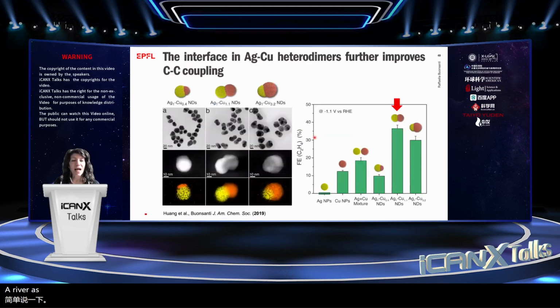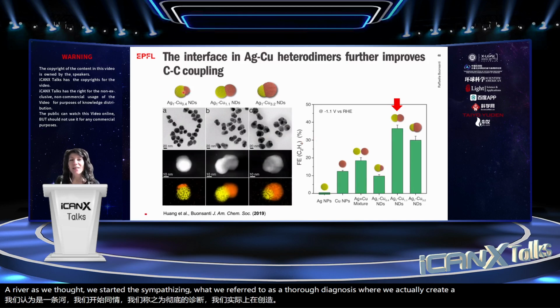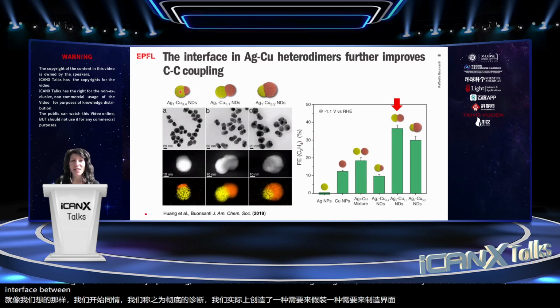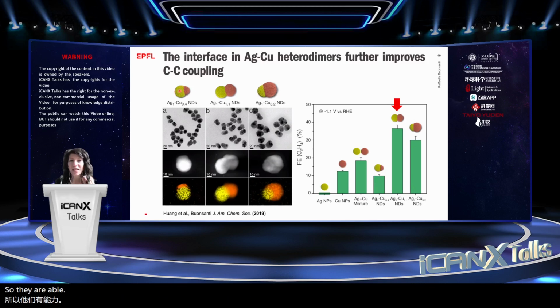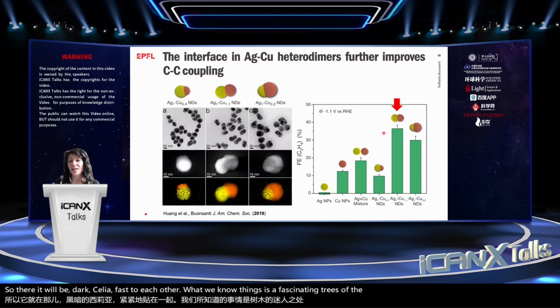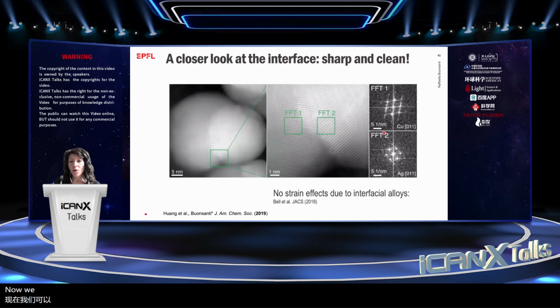However, as we started synthesizing what we refer to as heterodimers, where we actually create an intimate interface between the silver and the copper, so they are heteroepitaxially attached to each other, what we notice is a further increase of the Faradaic efficiency towards ethylene. Now, we performed some analysis on the as-synthesized particles, which revealed that we have a really clean and continuous interface between the two particles.